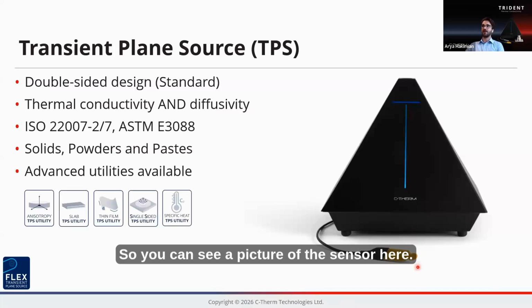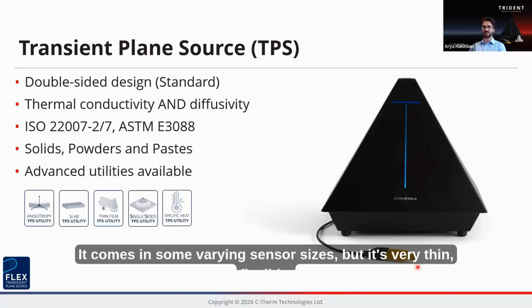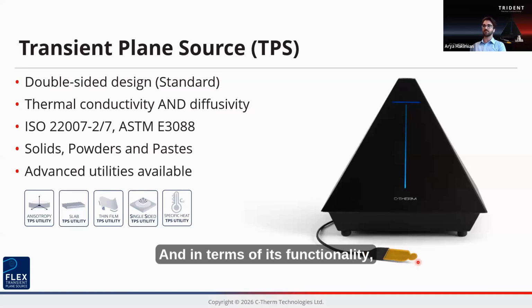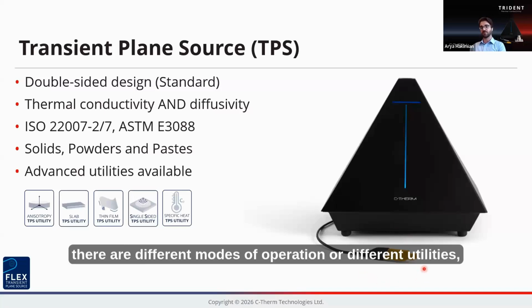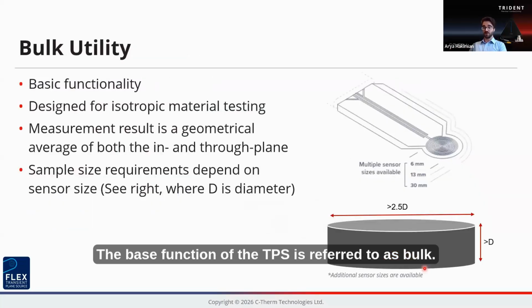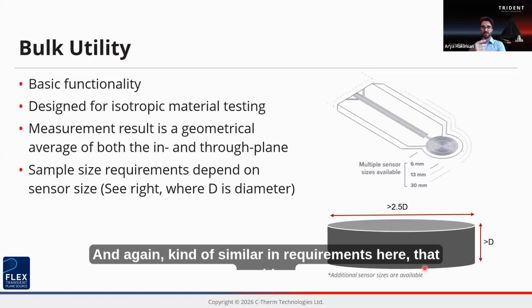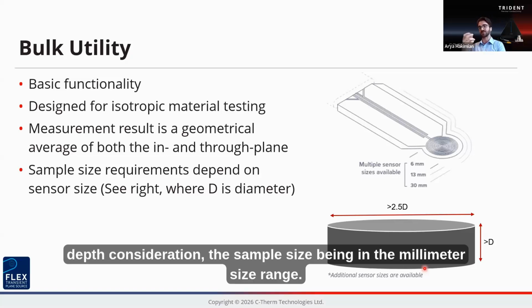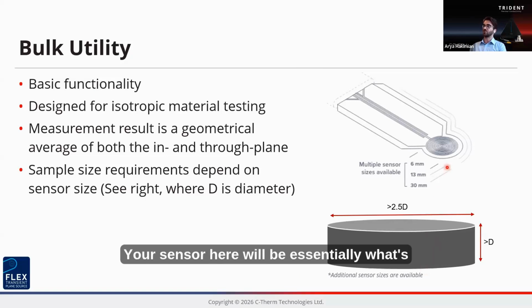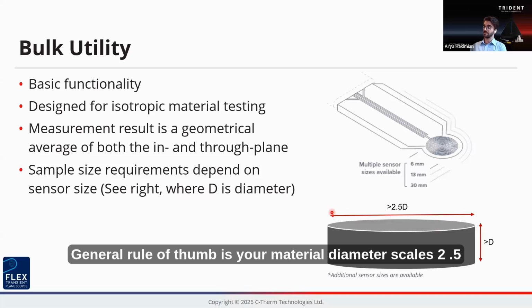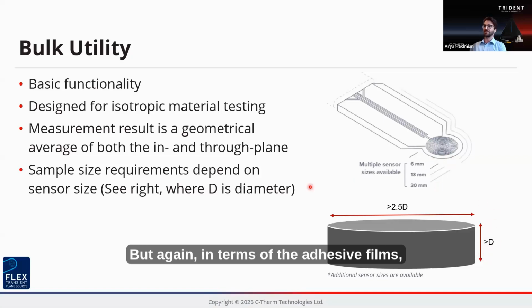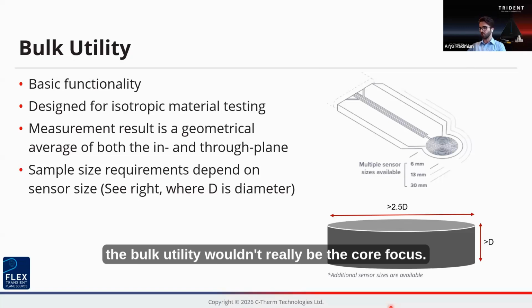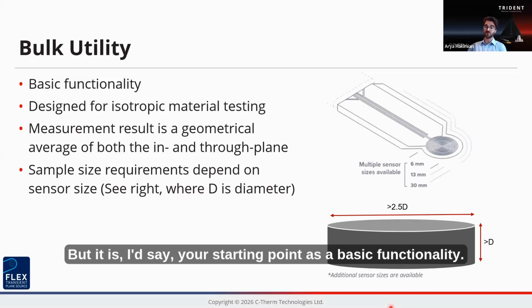So you can see a picture of the sensor here. This is a double-sided sensor, comes in some varying sensor sizes, but it's very thin, flexible. And in terms of its functionality, there are different modes of operation, or different utilities, as we describe them, that you can get access to. The base function of the TPS is referred to as bulk. And again, similar in requirements here, that probing depth consideration, the sample size being in the millimeter size range. Your sensor here will be essentially what's dictating your sample size requirements. General rule of thumb is your material diameter scales 2.5 times the diameter of the sensor that is chosen, with a thickness scaling 1 to 1. But again, in terms of the adhesive films, the bulk utility wouldn't really be the core focus, but it is, I'd say, your starting point as a basic functionality.